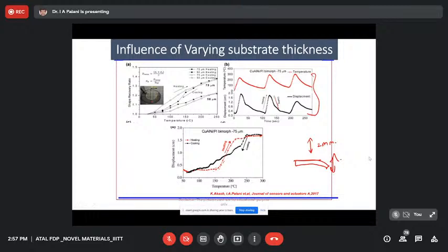In fact, the main motto of doing this experiment is that we want to vary the substrate thickness, because we have two materials taking part: one is polyimide and the other one is SMA. When two materials take part in my functional aspects, if I increase my polyimide thickness, I can go for a slightly higher order frequency. Basically, if I want a higher order frequency, I can vary my thickness appropriately, or if I want a lower order frequency, then I can go for a lesser thickness. So we want to investigate the influence of different thickness.